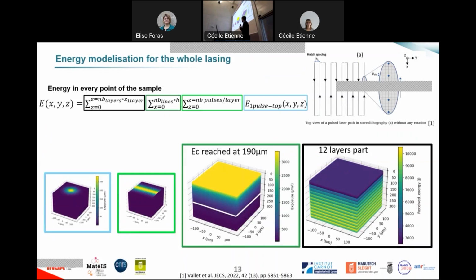So based on this model, I then add all my pulses. Here there are also a few parameters I can change to make the distances vary between the different pulses, and to vary the line spacing to make my part homogeneous. Here you can see it going from one pulse to one line to one layer. You see the layer is very homogeneous in terms of energy, so it's nice. And here Ec is the critical energy, and what I have seen with these parameters that I have chosen for the demonstration is that we reach this energy even at 190 micrometers, so much lower than several layers.